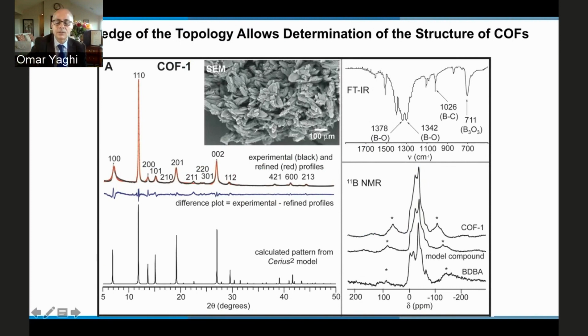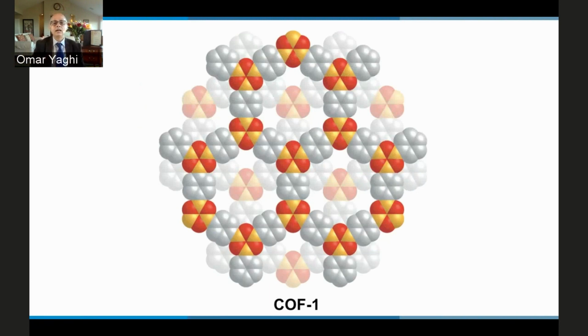We also do spectroscopy to confirm that the bonds that are linking these molecules together do form. And from NMR, we can also do the same, in this case, boron 11 NMR, which gives us information about the yield of the polymerization or of the reaction. So this COF basically has a graphitic structure where the layers are slipped with respect to each other, but this is the first 2D extended structure made entirely from covalent bonds.